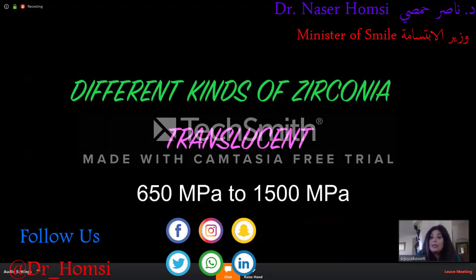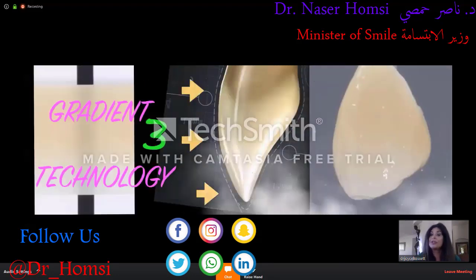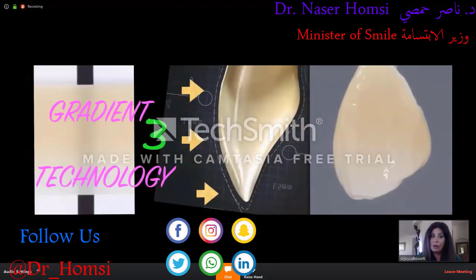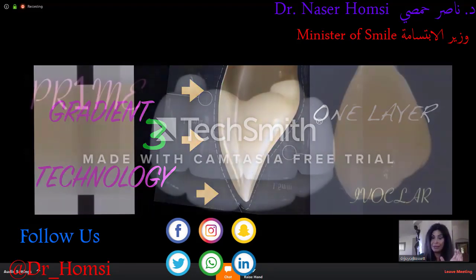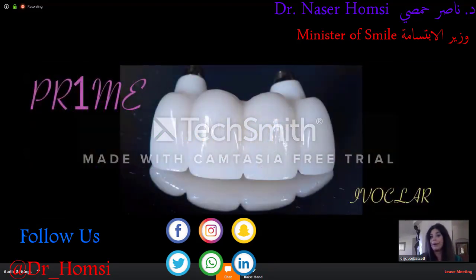Now there's new materials out there. There's zirconias that are translucent. They're getting more beautiful. So if you do full coverage restorations, these can range from 650 to 1500 megapascals. And there's a new product out right now by Ivoclar that has gradient technology, and they have all 3 layers in the same puck. It comes out in 1 layer, and that's called Prime. And I'm utilizing that for all my anterior bridges now.